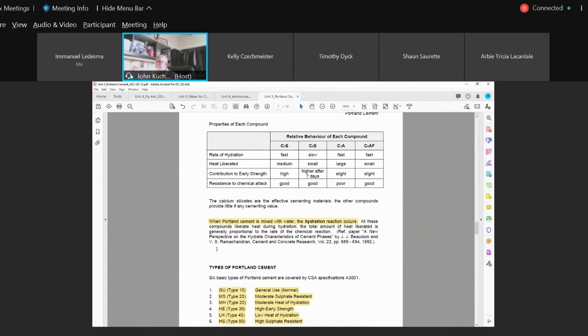When Portland cement is mixed with water, the hydration reaction occurs. That's why as soon as at the batch plant the aggregates and cement come together, even before the mixing water is added, there's probably enough water in the aggregates, especially if the moisture contents are high, hydration is going to start right from that point.